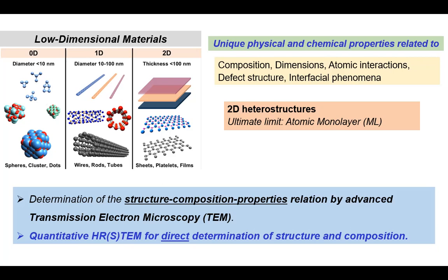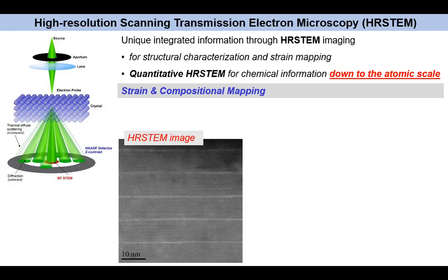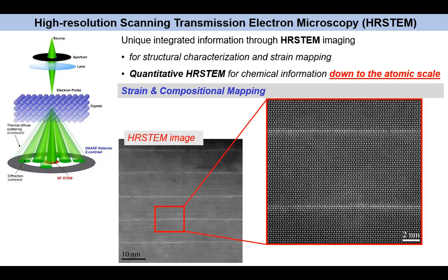And the quantitative high-resolution TEM or high-resolution scanning TEM can allow us a direct determination of the structure and composition. In other words, we can directly visualize and measure the structure and the composition. So, especially regarding high-resolution scanning transmission electron microscopy, it is possible to see the structure, measure the deviations of the atomic positions from the equilibrium positions, in other words, measure the strain field, and at the same time you can also use the chemical contrast, like you see here, to differentiate the chemical composition and measure quantitatively the chemical composition, and you can do this down to the atomic scale.